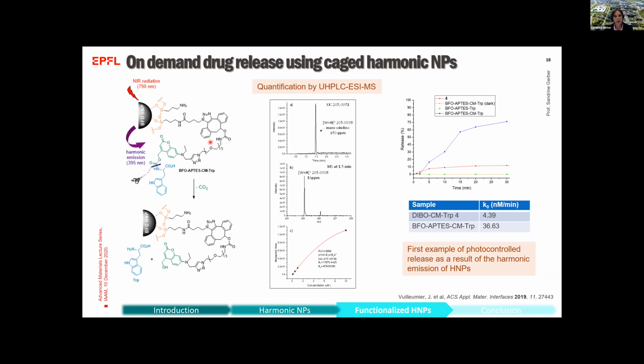So then we irradiated the nanoparticle at 750 nanometers, and we observed that the harmonic emission was able to trigger the release of tryptophan, which was quantified by mass spectrometry using UHPLC, ultra high performance liquid chromatography.